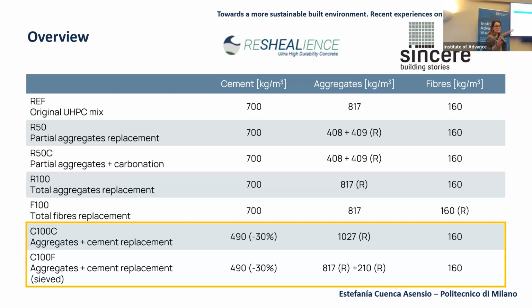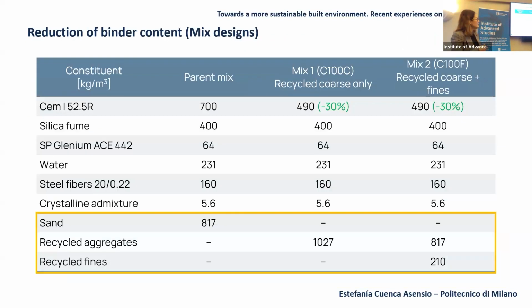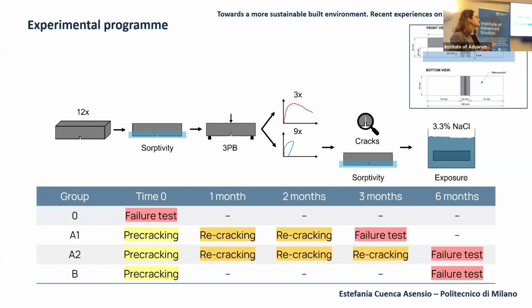Maybe not all of you are familiar with ultra-high performance concrete. The coarse aggregates in this kind of mix are around 2 millimeters, so everything passes a 2 millimeter sieve. In this case, we also have fines, which are aggregates that pass a sieve of around 75 microns. So it's really thin. Here you can see the mix design of these two concretes, and you can see the quantity of sand, recycled aggregates, and recycled fines with reduced binder. And this is the experimental program.